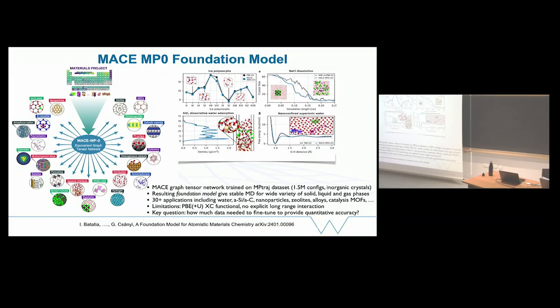For example, layering of water at a silica interface. So you take a crystal of silica and you put some water and you have an interface between water and silica and you look at the density profile and it's actually pretty good agreement with, and there's no DFT on here. Many of these things are in surprisingly good agreement with DFT. These are different polymorphs of ice. So without directly fitting on any ice, only fitting on inorganic crystals, the relative ordering of different polymorphs comes out surprisingly well.